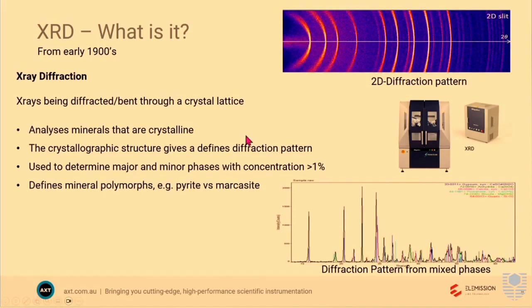So it analyses materials that are crystalline. So you have to have crystallinity, you've got a crystal structure. So the crystallographic structure defines the diffraction pattern. Now, it's used to determine major and minor phases if the concentration of that phase is over 1%. So if you've got trace minerals, it won't detect them because they're below the detection limit of the instrument. And it defines crystal polymorphs.